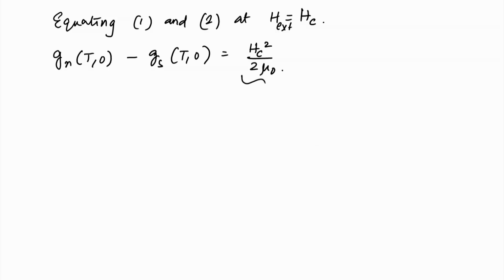So, this is positive, and because this is positive the superconducting state is more stable than the normal state below H equal to H c.